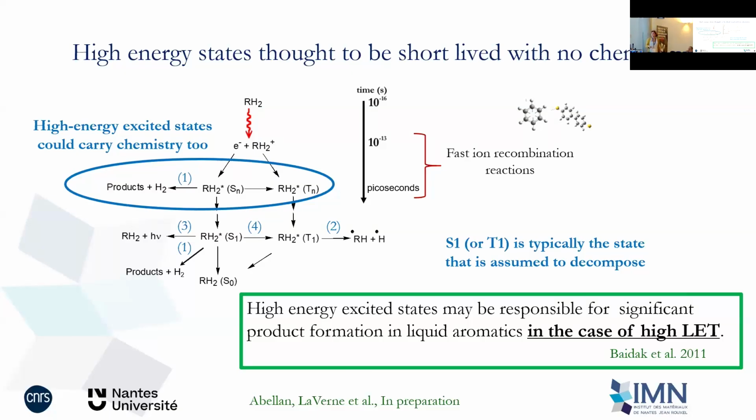And this is what we think is happening: the high energy excited states in the microscope, if you really have very high dose rates, and because of this interaction when you are scanning your material, we are depopulating the singlet excited electronic states because you are producing damage with the high energy. This energy is going somewhere else, so they carry chemistry. This is what we believe.